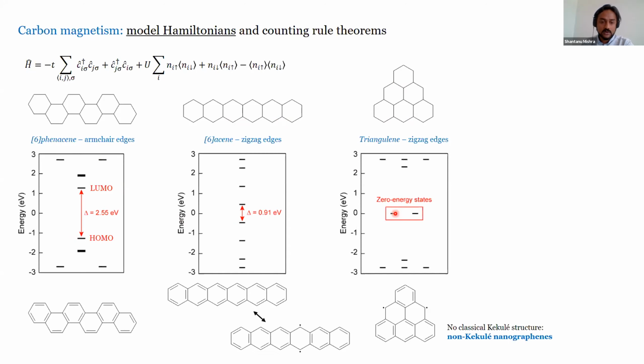Now, the chemical consequence of this is that a chemist would write the structure of phenacene as shown by my pointer, and it would consist of 3 aromatic sextets. The acene would consist only of 1 aromatic sextet, which can, however, migrate throughout the molecule. And one could also potentially write it as a resonance structure between a closed shell form and an open shell form, where you have increased the amount of aromatic sextets. Finally, for triangulene, you see that there's no way one can write a classical Kekulé structure without leaving these unpaired electrons. And so we're going to refer to these as non-Kekulé nanographenes.